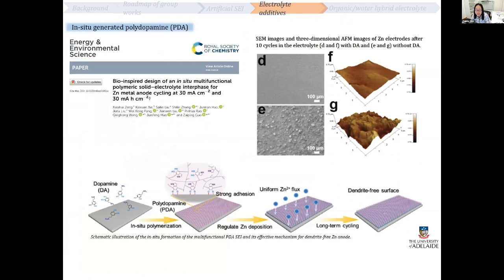However, this inorganic SEI is hard to form a film-like structure that fully covers the surface. And in the following cycles, because zinc plating stripping has a huge volume change, it induces mechanical strain. That mechanical strain could damage this inorganic SEI. To address this issue, we also try to create an in situ organic SEI with better integrity on the surface of